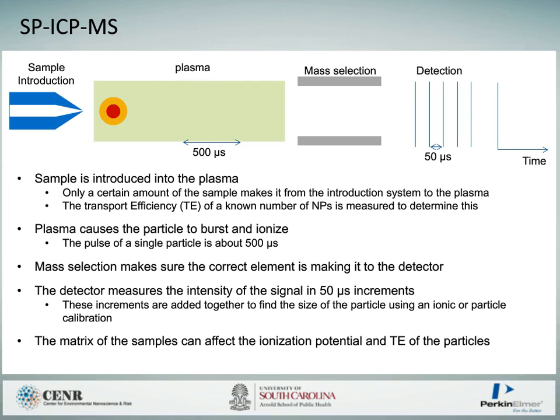Single particle ICP-MS is very similar to ICP-MS in that you have an introduction system with a nebulizer and a spray chamber, which introduces your liquid sample containing nanomaterials into the ICP-MS. We try to use a low concentration of nanoparticles, around 100,000 nanoparticles per mL, so that only one nanoparticle will enter the plasma at a certain time. The particle travels through the plasma, heats up, bursts, and ionizes. This moves through the mass selection process so we can take the element we are interested in to the detector. At the detector, we use a very short dwell time so that we can split the particle up into a number of different measurements. At this point, we read it as an integrated intensity, and from an ionic calibration, we can then go back and say how large our nanoparticle of interest is. The matrix of your samples can affect the ionization potential and the transport efficiency of your nanoparticles through this system, and I will discuss that in the next slide.